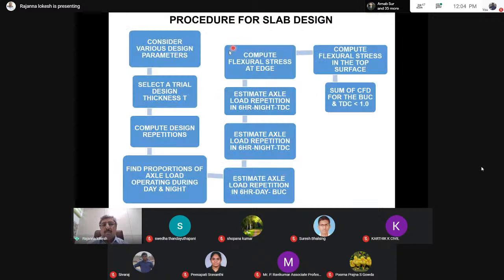So this is one slide which will help us in understanding the considerations that should be made. A flowchart where you are going to consider the design parameters. You are going to assume a trial thickness. You are going to compute the repetitions that are going to play, and provide the axle load data. Then, considering 6 hours night and 6 hours day, we are going to calculate bottom-up cracking as well as top-down cracking for the analysis. Compute the flexural stresses and then go with the check for fatigue. If it is less than 1, automatically the design is safe.